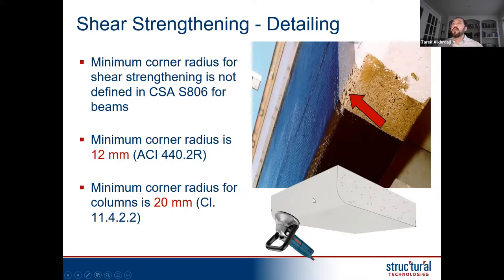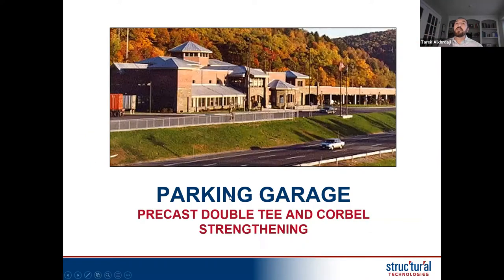And this can be easily done with the grinder most of the time. They grind it off to create that radius. And sometimes if a column, for example, or beam has a chamfer, a big chamfer on it, you can rebuild it with thick epoxy trowel that has radius, and you build that corner, create that radius.